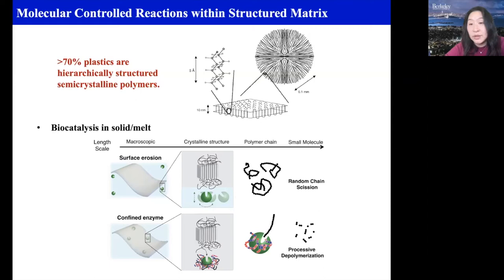But what you also see is that the enzyme in this case is in the viscoelastic melt. It doesn't really have a lot of freedom to float around, and it pretty much has to take whatever polymer chains are around. So it becomes a kinetically controlled reaction such that only when the enzyme can get to the substrate is the reaction going to happen. So it's a substrate diffusion limited process.